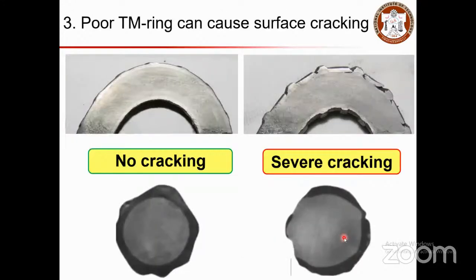Other than that, for these TM bars we need to have a surface cracking check. What we need to do is bend the bar and see if there is any cracking on the surface or not. We bend the bars like this. You can see the cross section here. This is the good cross sectional bar. When you bend a good cross sectional bar, you will not see any cracking on the surface. Whereas if the cross section is not good, that is, if the TM ring is not uniform, when you bend it, you will see a lot of severe cracks like this.